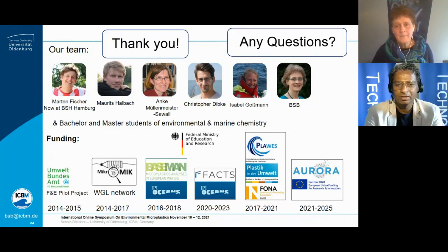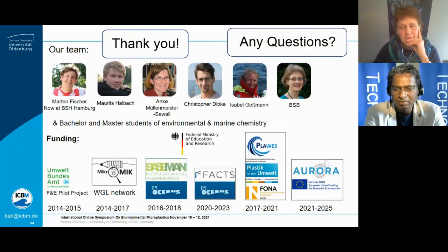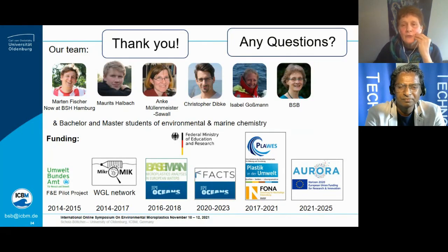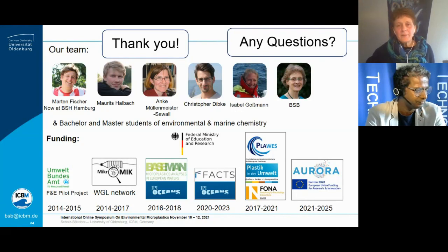Thank you. There's one more question here. When measuring using the pyrolysis GCMS, is there a probability to obtain inconsistent fragments? How can we define the characteristic of every mass fragment as a polymer identification? So you have to look definitely for interferences also with natural material. For example, in the first presentation today, the styrene monomer is completely unusable because it's generated from chitin. And you have a lot of others where you can be sure.